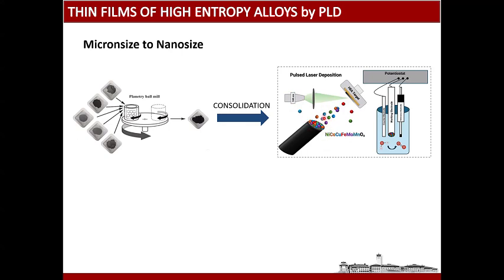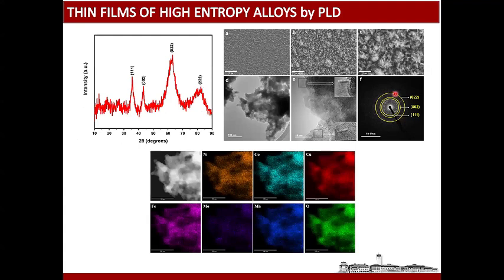So we have deposited these high entropy alloy thin films by using pulse laser deposition, and then we use these electrodes in our electrocatalytic applications. So this again gives an FCC structure in addition to the BCC structure, and then we have a more porous structure and nano-sized particles, as you see from these electron microscope images and also from transmission electron microscope images. And as you see also, we have homogeneous distribution of all metals in the structure according to this EDX analysis.